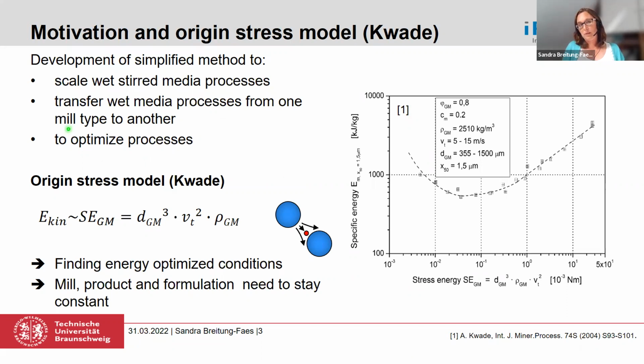And my starting point was the original stress model by Kwade. He said that colliding grinding beads have a certain kinetic energy, which is proportional to their mass and to the grinding bead velocity. This grinding bead velocity is usually not available, so we don't know it, and we can't measure it in a mill. So the idea was to set it as somehow proportional to the stirrer tip speed, which is a typical operational parameter in a stirred media mill. And so he came up with the stress energy of the grinding beads.